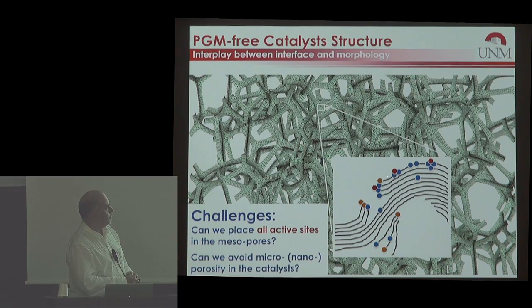I have put here orange as oxygen, blue as nitrogen, and red as iron. And I put oxygen here too, because oxygen-modulated or oxygen-terminated carbon is also a catalyst for oxygen reduction to peroxide, and it could be a catalyst for peroxide reduction to water. So participation of the oxygen moieties in this catalysis, especially under the assumption that there are multiple active sites, is not to be ruled out. And these materials are highly oxygenated.